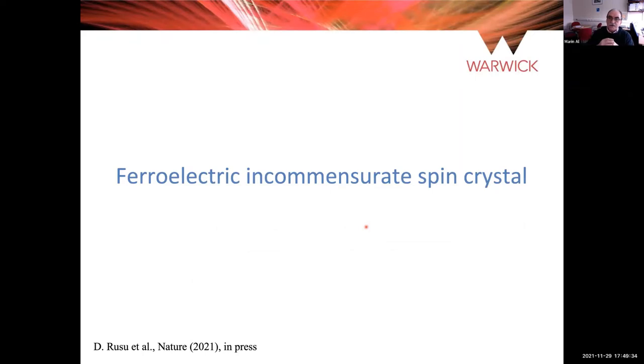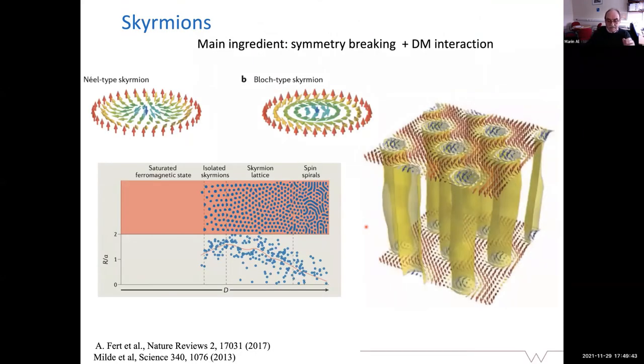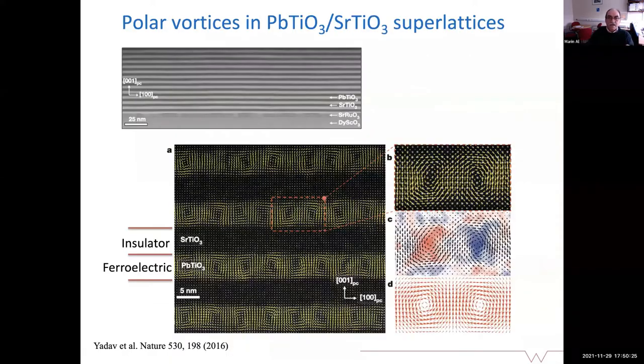But we're looking at these topological phases in ferroelectrics per se. I'm drawing your attention mostly to this range of this nice plot, where we have skyrmions, which are isolated, and we have a skyrmion lattice, which normally gets into a hexagonal lattice. And that goes into a kind of spin spiral, decaying into that type of cycloid of hexagonal phase I've been showing you. And we've learned pretty much in the last years, from Ramesh's work at Berkeley, that such kinds of chiral phases do occur in ferroelectrics as well.